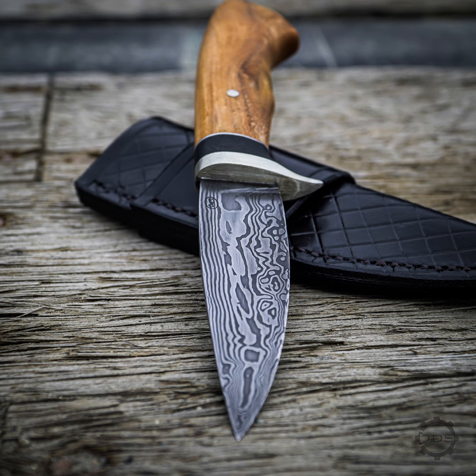It's extremely hard. And what happens with the shoulders of this blade? Well, you just stressed them out really bad because you quench the whole thing. If it's a full quench blade, which mine typically aren't, you just stressed it out really bad. You've got square inside corners. Those want to crack, right? And then let's say you do a minimal temper to it, because your blades are known for holding an edge and they're known for being really, really hard. And then your blade from tip to tang is fully hardened, it's extremely hard because you do a minimal temper, and then somebody abuses it and it shears off right there.